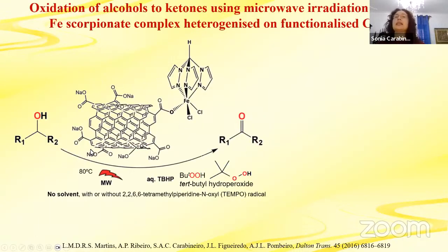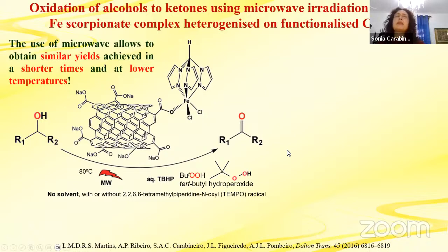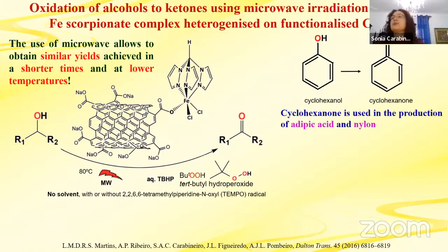We also use this complex heterogenized on carbon nanotubes for the oxidation of alcohols to ketones, which is another process of industrial importance, but this time using microwave irradiation, okay? And here we used 80 degrees and aqueous terbutyl hydroperoxide. No solvent was needed because the solvent was the alcohol itself, and with or without this radical, the so-called tempo radical, okay? And the use of microwave usually allows to obtain similar yields in shorter times and lower temperatures. So it was tested for this reaction, the oxidation of cyclohexanol to produce cyclohexanone, okay?